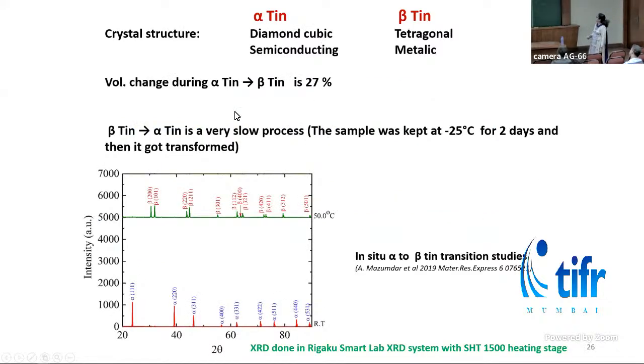Alpha tin has diamond cubic structure. It is semiconducting in nature. Beta tin has tetragonal crystal structure. It is metallic in nature. When alpha tin changes to beta tin, it changes volume by 27%. And beta tin to alpha tin transition is a very slow process. This happens at minus 25 degrees centigrade. We kept the sample for 2 days, and then we could see this transformation happening.